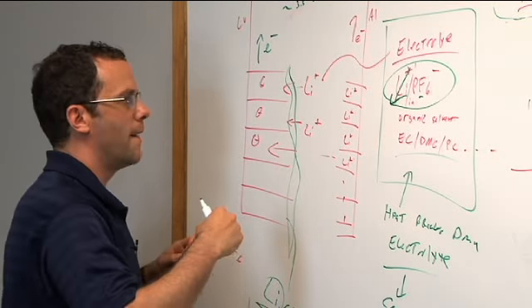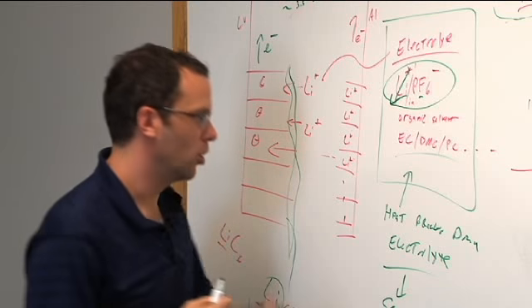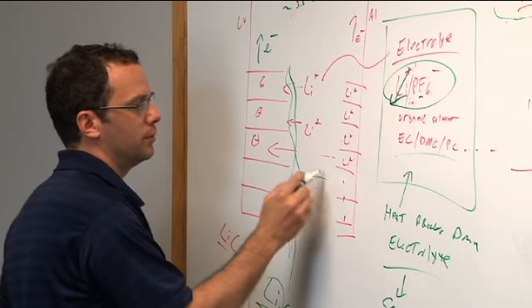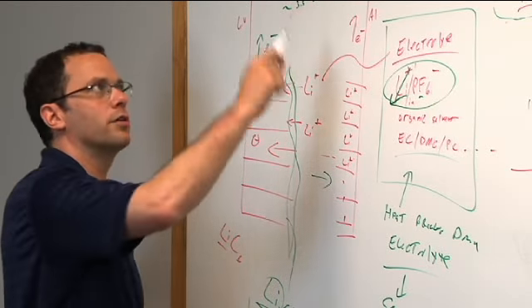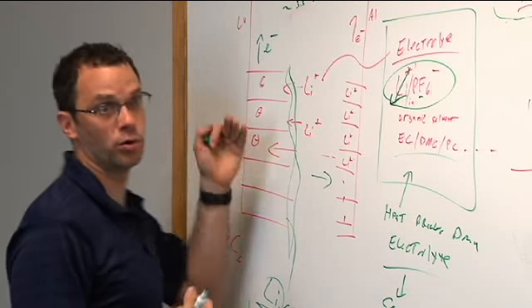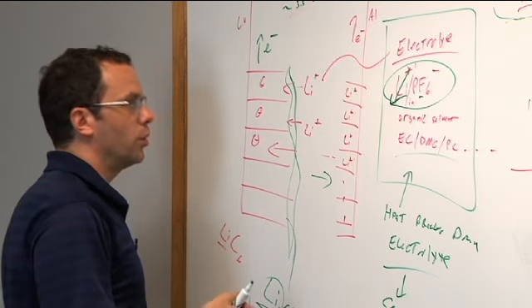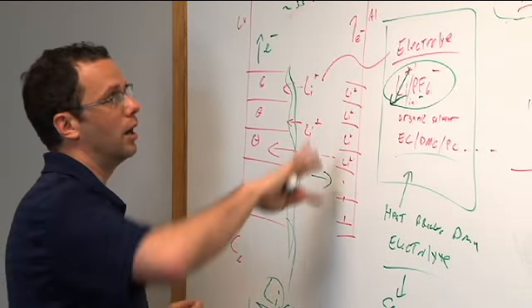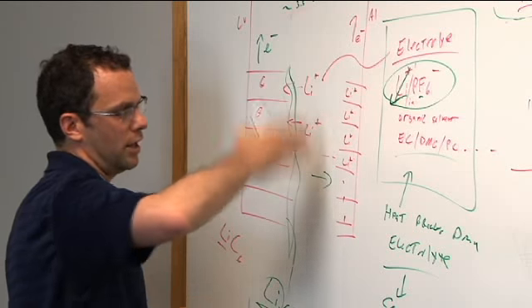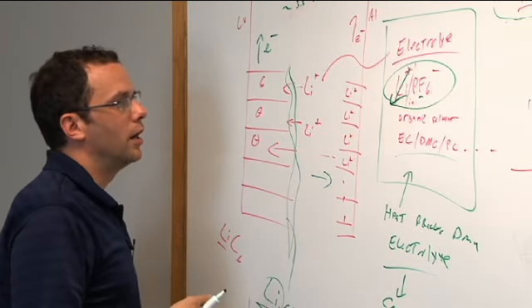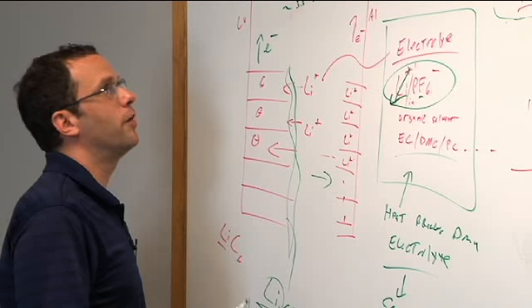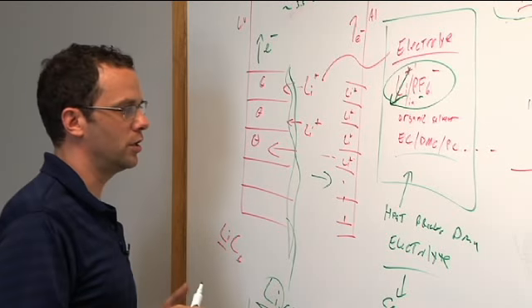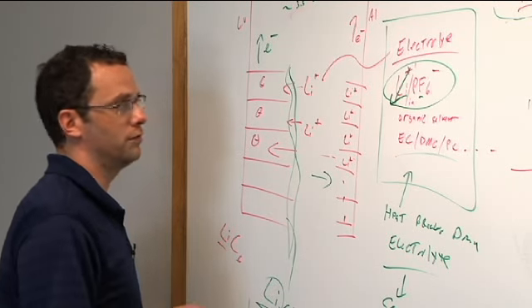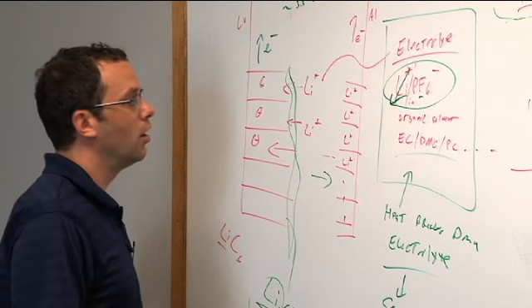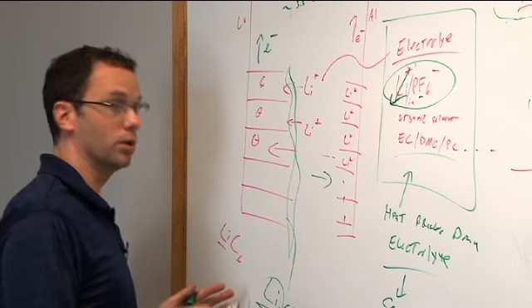So if you actually let it go below that, you could be plating lithium onto your cathode because you're driving more lithium over than it wants to be, or you could be causing some other decomposition or phase evolution on the cathode side. In my experience, lithium iron phosphate is relatively stable to over discharge. Now, if you really over discharge it to a negative voltage, all bets are off. I would avoid going below 0 volts.